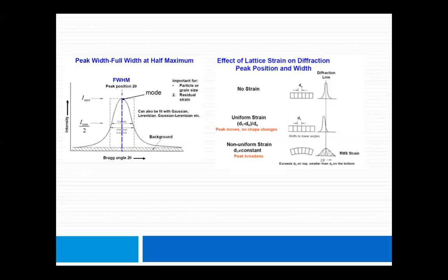So what will happen? XRD will give you the resultant of these three things, so you get the peak broadening. So what I want to say is, the peak broadening happens because of three things: first, particle size or crystallite size; second, stresses; third, instrumental error. Okay, for a rough estimate, it's okay, you need not do this. But if you want precise results, it is better to do the correction in the formula.